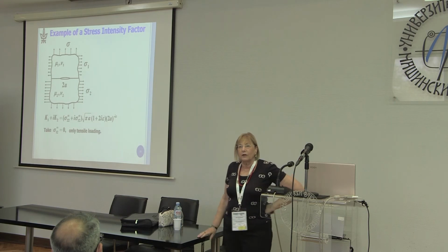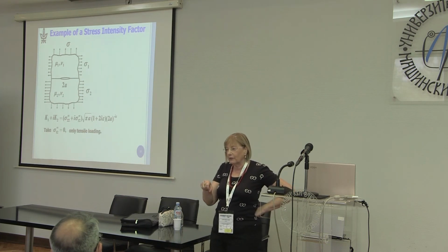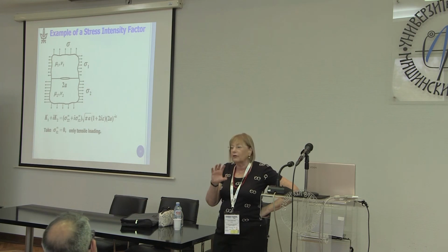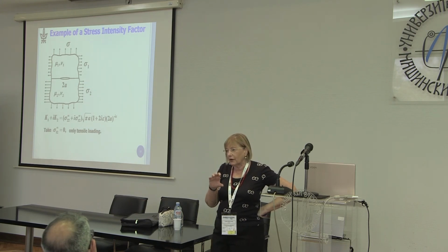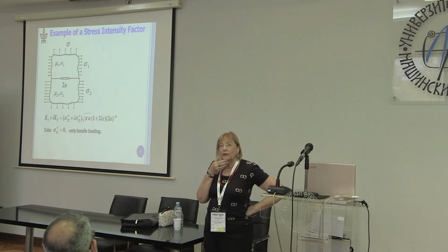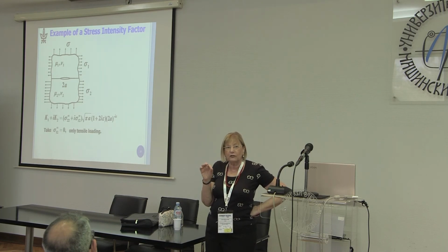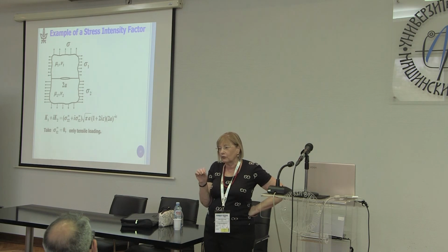we have calculated the M integral in the elements close to the crack tip, the 4 elements surrounding the crack tip. And actually, we don't get very good values for it, but it's not, in my opinion, because of the oscillation. It's because we're using, even though they're 8-noded, I didn't say this, I will say this later, 8-noded isoparametric elements when we calculate stress intensity factors. And we move the nodal points adjacent to the crack tip to the quarter point, and we get a square root singularity. And when we do that with isotropic homogeneous material, not two materials, we're describing pretty well the square root singularity.